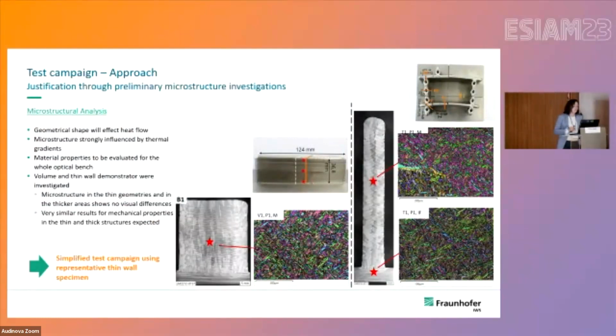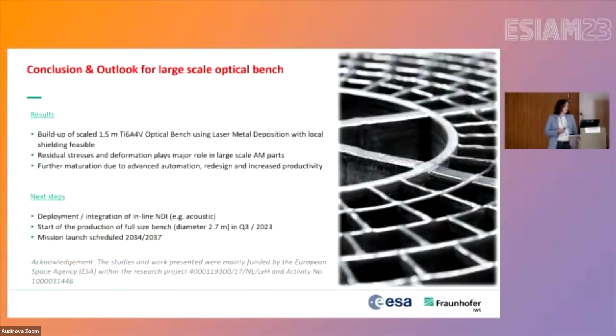Interestingly, what we have seen here is that the microstructure in the thin geometries and in the thicker areas shows no significant visual differences. I have to say that we also integrated intermediate heat treatments during the process, so this seems to compensate for some of the issues of the expected thermal gradients. And we had very similar results from the mechanical properties. So in terms of saving time and resources, we moved to the thinner wall approach to follow up all of these fatigue and mechanical properties.